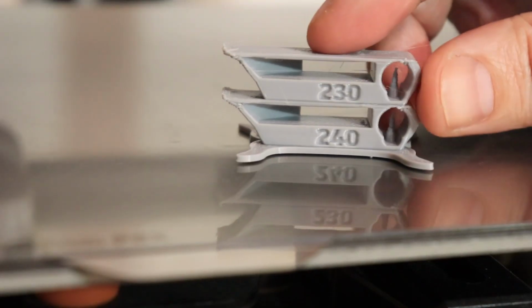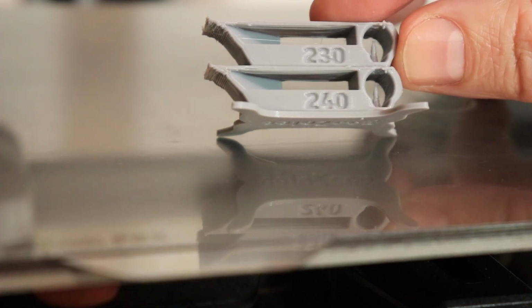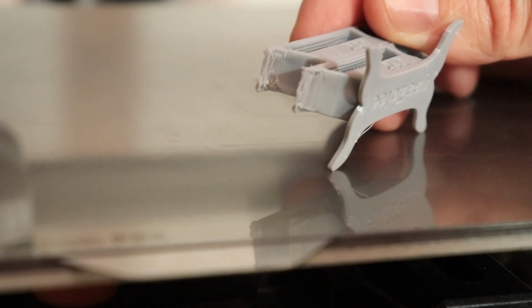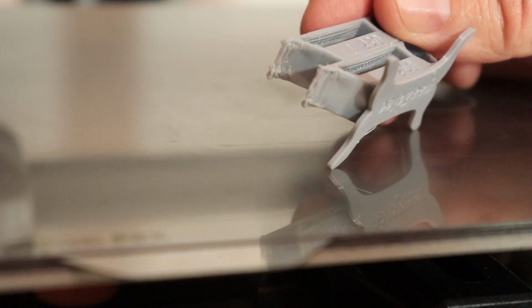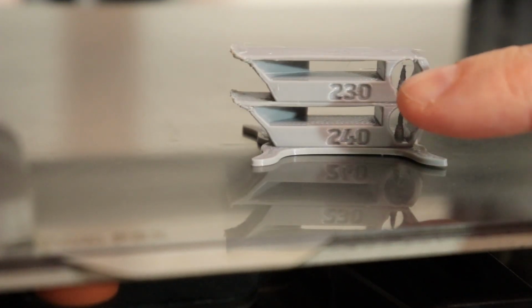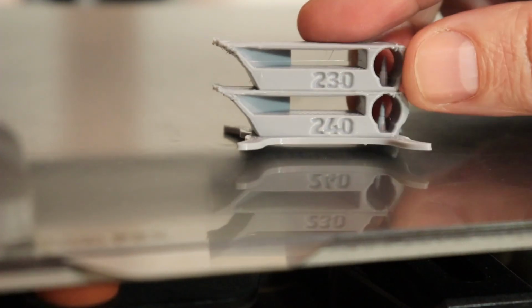But for the first look it looks okay, the bridging is great and absolutely no stringing, so this means the filament is dry. The only problem I can see is with this overhang, and the reason for this is the weak part cooling. 15%, well, it's even more than suggested, because they said no cooling at all. So the test specimens will be printed at 235 degrees Celsius.